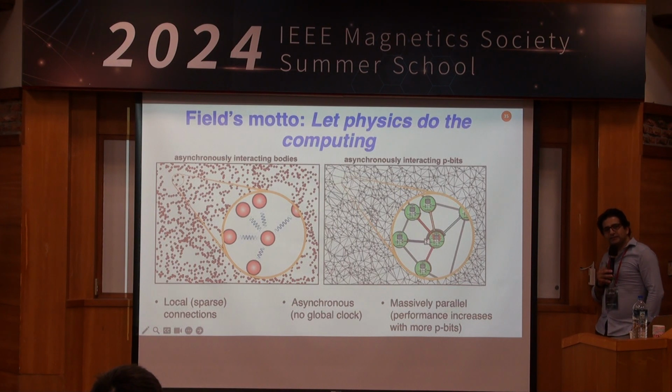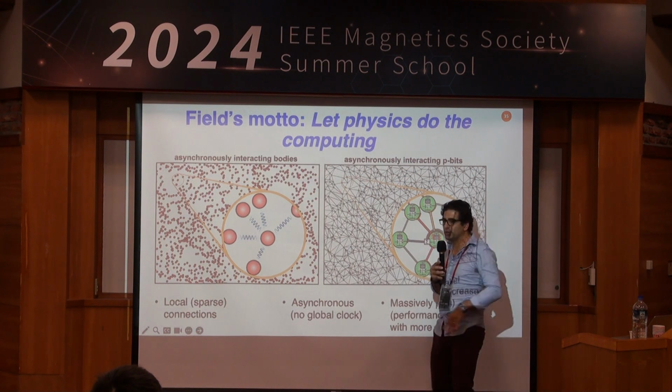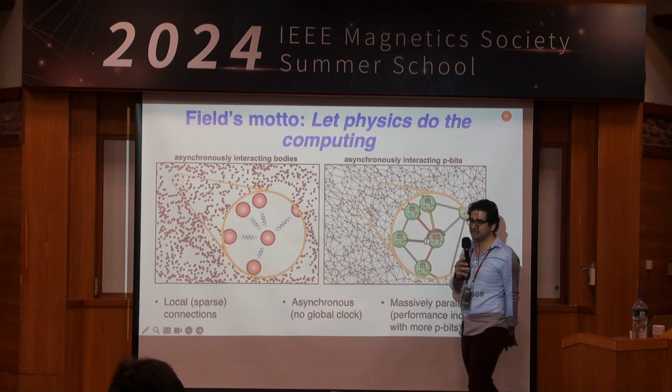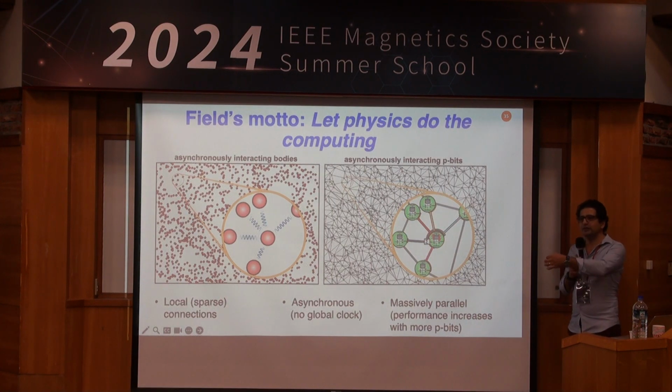I think there have been a lot of ideas, and beyond ideas, a lot of experimental demonstrations now. If you're a PMA, first of all, you don't have to be exactly 0. You can be close to 0 and it'll still work. Circular magnets are my favorite. It's almost like you have no anisotropy in the plane, but you can't go out of the plane, like a random clock pointing.